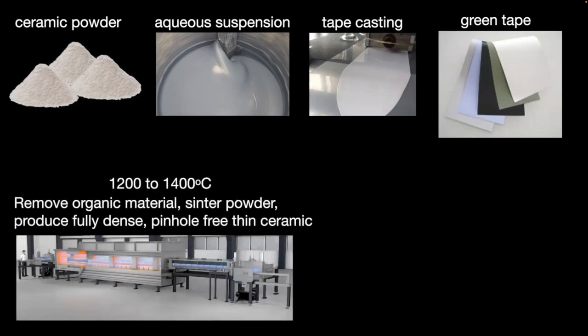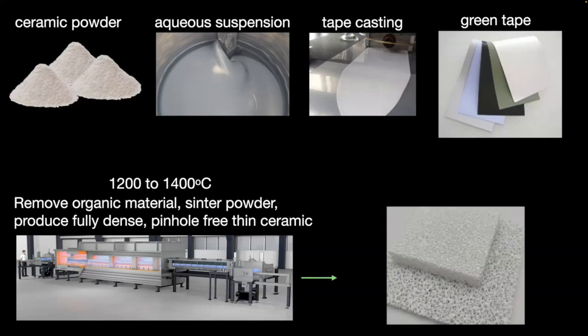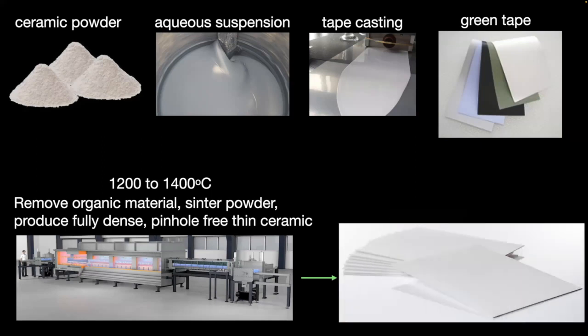Now you have to remove that binder. All of the organics have to be removed. That's typically done at 300 to 400 C. And then you have to densify this material to something that has no pinholes and is hopefully 20 microns or thinner. That is not trivial. And quite often when you try to densify ceramics, they open up pinholes. So if you're making a porous material, okay, that's easy. If you're trying to make a thin, flat, dense, pinhole-free ceramic membrane, that's not trivial.